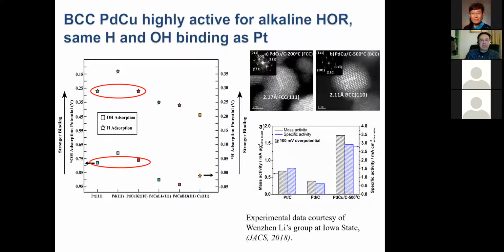Here we worked with Wenzhen Li's group at Iowa State, where he looked at different forms of palladium copper, and he found that if you form the specific palladium copper intermetallic, a body-centered cubic structure, we got about the same hydrogen and hydroxide binding energies as we did on platinum, and a current density, with cheaper metals, or hopefully cheaper metals, the price of palladium being variable, that was as high as platinum.